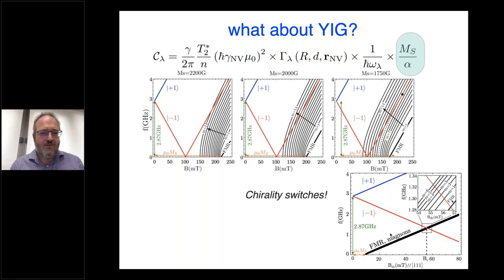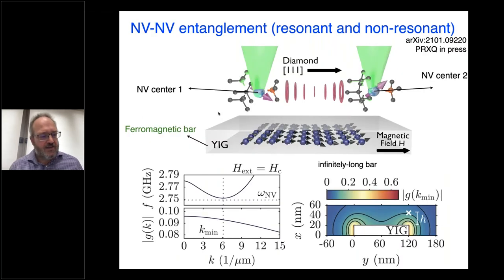If you compare these curves of intersection of the NV transitions with those for V[TCNE] down below, you can see that the chirality of this transition has changed. It's very difficult to get a resonance with a magnon mode that's reasonable, that has an azimuthal quantum number of 6 or 7, rather than very, very high. And even then, the chirality has switched. So that's a challenge for this situation.